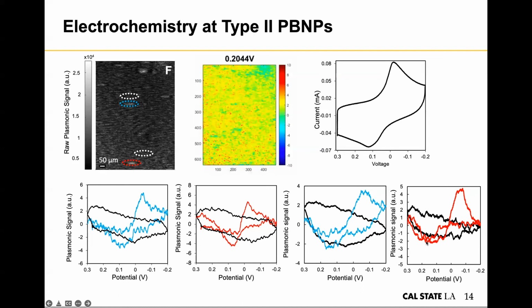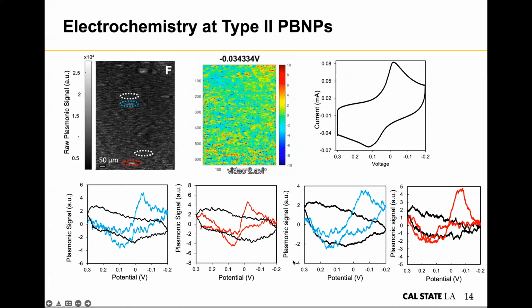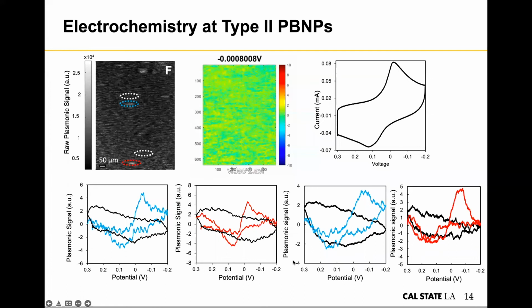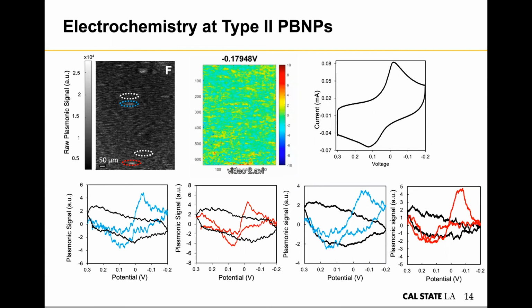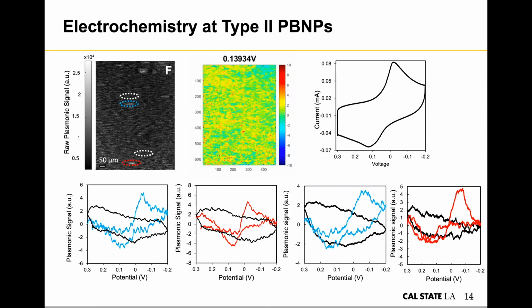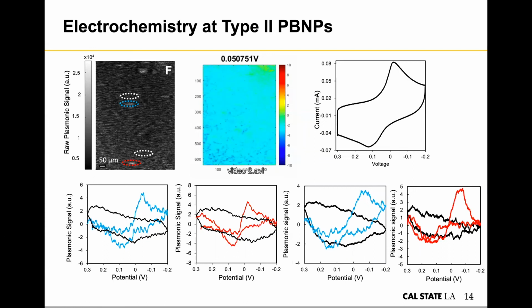So we think that it's probably due to the PVP residues on the Prussian blue nanoparticle surface that prevent the potassium ion from getting in and out of the lattice to realize the reaction. At the same time, it might block the contact between the Prussian blue nanoparticle and the gold surface for the electrochemical reaction. So what my student did next is they tried to remove the PVP by ethanol, by acetone, with different methods, and see whether there's any improvement in the signal.